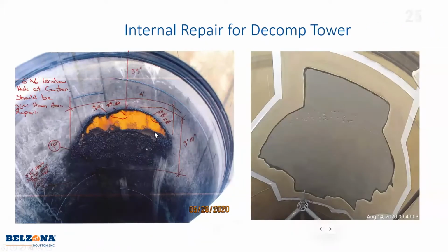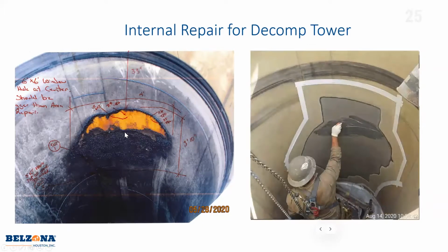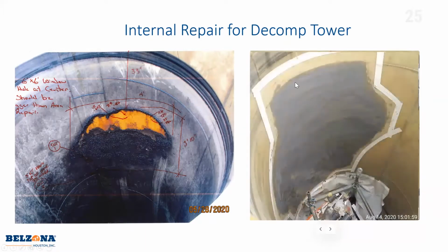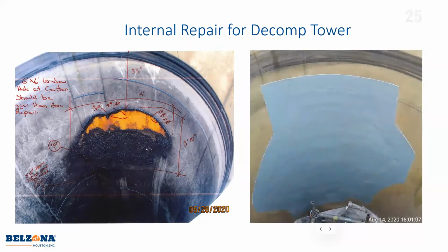This is a particular one here. They actually had a Halar coating with a rubber liner underneath, and it was burned during the upset. So this one is more like a repair. We came in and just did a localized repair. This rubber liner was about a 1/4 inch thick, so we used our paste grade material to make it flush with the Halar coating. That's what they requested. And then we applied two coats of a system that can handle what was running through the pressure vessel.